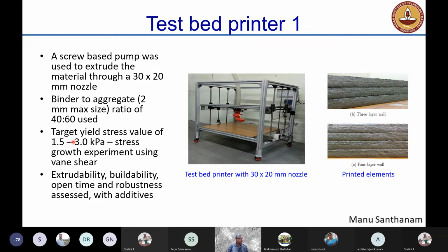Now, target yield stress values are of the range of 1.5 to 3 kilopascals, just to give an indication of normal concrete that is vibrated. Okay, vibrated normal concrete will have a yield stress of around hundreds of pascals. When you talk about self-compacting concrete, the yield stress will be nearly 0 pascal. So here we're talking about 1.5 to 3 kilopascals, which is totally different as compared to SCC or normal concrete.